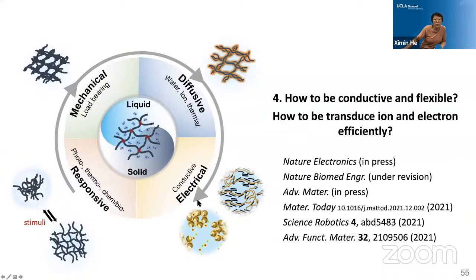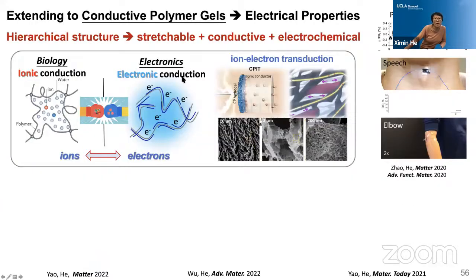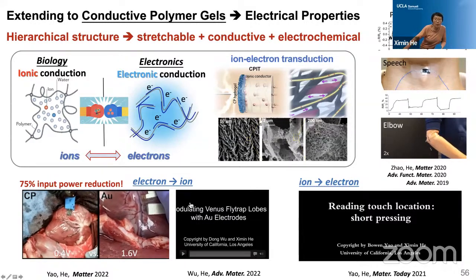So with this, I wanted to quickly show that, beyond the basic mechanical and diffusive properties, we can also construct gel out of a conducting polymer, so that not only can it be ionically conductive, it can also be electrically conductive, which may be a very useful interface material between bioelectronics and tissue. We know most biological signal transduction utilizes ion conduction, while our man-made electronic devices utilize electrons, right? So at the interface, when we attach bioelectronics onto tissue, there's actually this conflict, so the interfacial impedance is usually pretty high and consumes energy and distorts the signal detected by the electronics. Therefore, we thought about developing conducting polymer hydrogels with both ionic conductivity and electrical conductivity and mechanical compliance. Hopefully we can make a better interface.